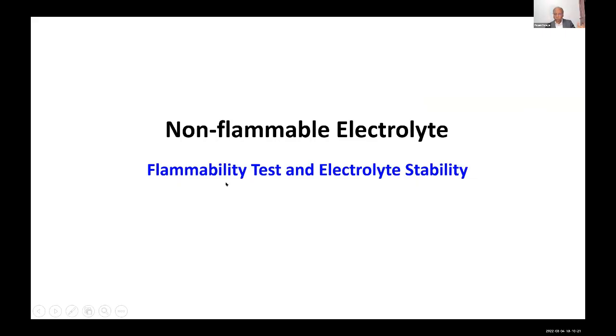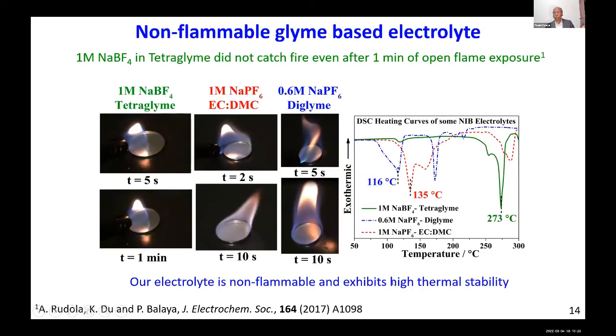The electrolyte is non-flammable and it is also thermally more stable. You see here, this is the tetraglyme-based electrolyte, glyme-based electrolyte. And if you bring any fire, it basically doesn't catch fire even for 60 seconds. Anything that does not catch fire beyond 20 seconds, you can categorize as non-flammable. Whereas the carbonate-based electrolyte, which is widely used globally by any industry that I just now referred to, they all catch fire in about 10 seconds to 15 seconds. So non-flammable electrolyte, first point.